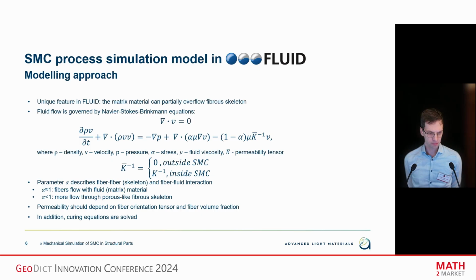And yeah, depending on the choice of these parameters, this controls the speed difference between the flow of the fibers and the resin. And then, of course, what we need then is also a permeability tensor, and this was one of the first purposes where we used GeoDict for in this project, was to estimate the permeability tensor, which depends on the fiber orientation and the fiber volume fraction.